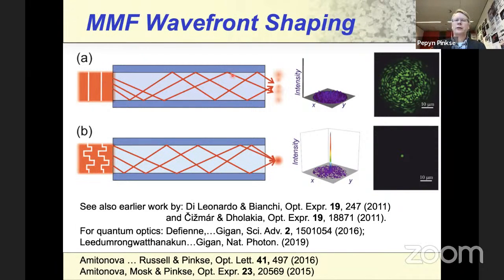So this is also something that complicates imaging through a fiber. However, you can use techniques known from what we call complex wavefront shaping, invented here in Twente by Allard Mosk and Ivo Vellekoop, to actually invert the path of light. If you know where to focus and how the light would come out if you put a light source here, then you can, vice versa, inject light with this wavefront and get a focus on the distal end of the fiber. And so it's possible to make a very sharp focus at the end facet of this fiber.